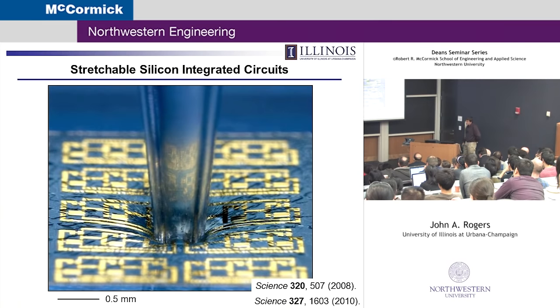So that's the idea, to give you a sense of the mechanics. The point is that kind of concept scales nicely straight up to the circuit level. So you can take not just ribbons of silicon, you make an ultra thin integrated circuit, bond it to a biaxially pre-strained piece of rubber, relax it, you get a much more complex distribution of buckling patterns, but one that can, again, accommodate large strain deformations in a way that avoids fracture in the circuit materials themselves.